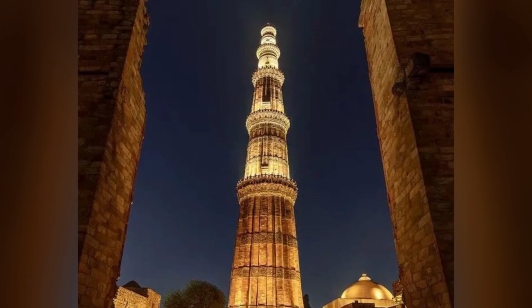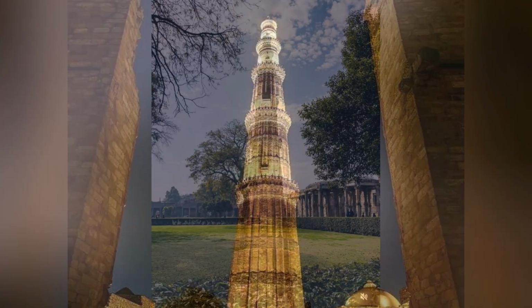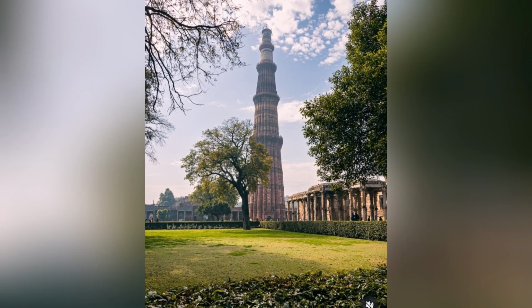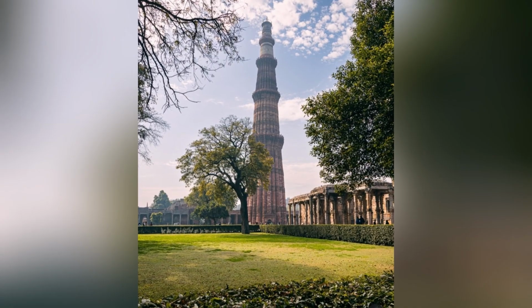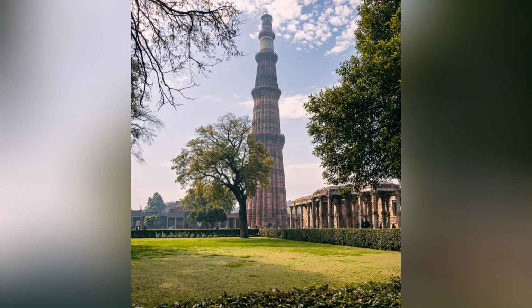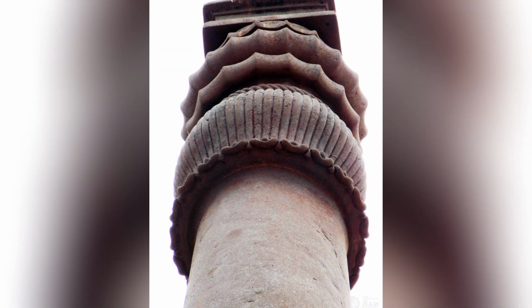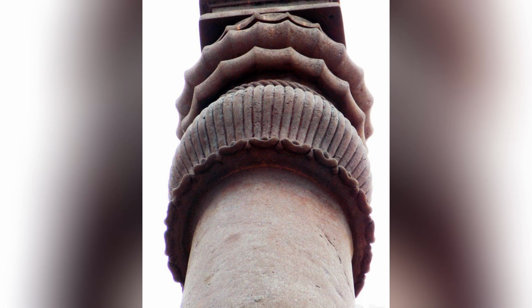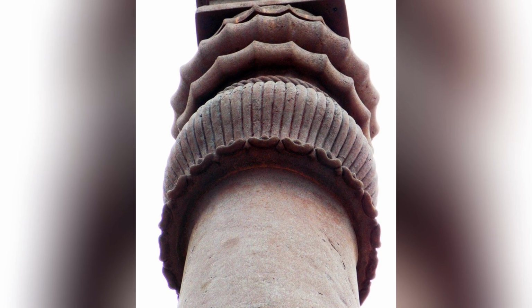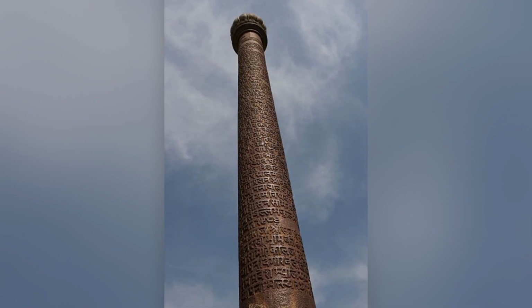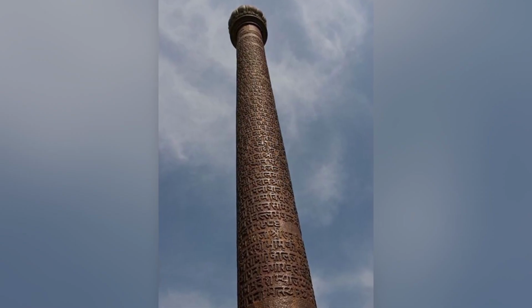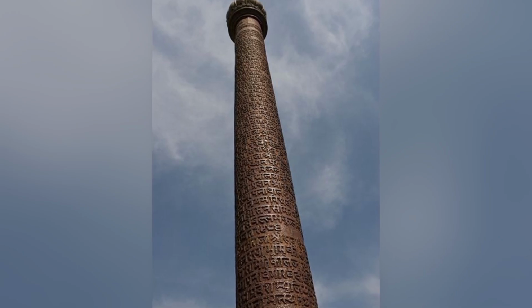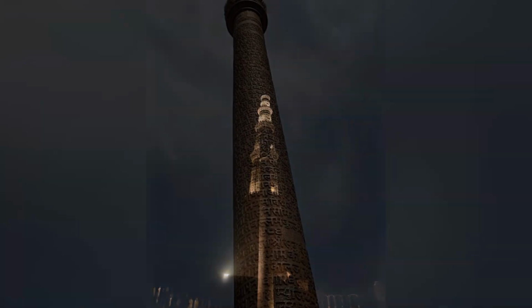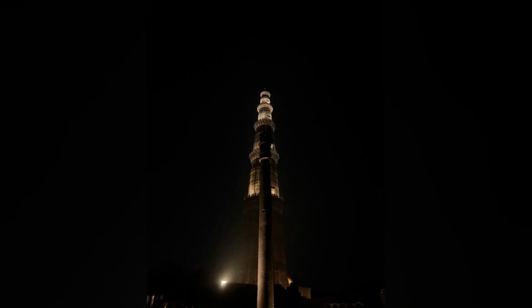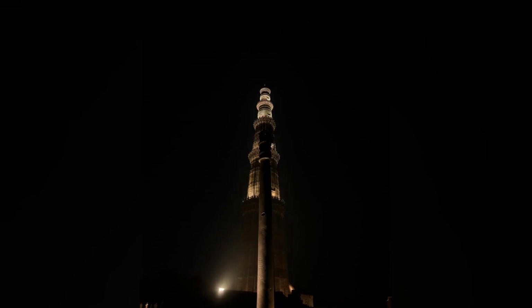The research of Balasubramaniam, which was published in a series of papers beginning in the late 1990s, identified the missing factor, the phosphorus. Balasubramaniam's analysis of the protective film on the pillar's surface showed that the film was not ordinary rust, not the iron oxide that forms on corroding iron, but a compound of iron, phosphorus, hydrogen, and oxygen, specifically iron hydrogen phosphate hydrate, the mineral known as misawite. The misawite film was dense, adherent, and impermeable, forming a continuous barrier between the iron surface and the atmosphere that prevented the moisture and the oxygen from reaching the metal, and that thereby halted the corrosion process.